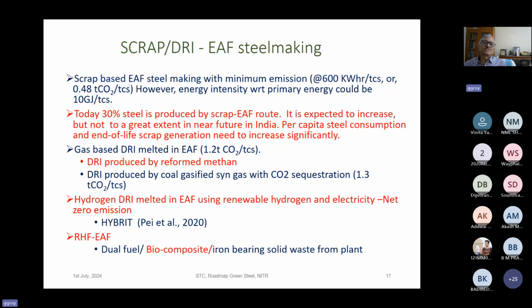Then the scrap EAF steel making. The scrap-based EAF steel making with minimum emission is around 600 kilowatt hour per ton of crude steel, which corresponds to around 0.48 ton of CO2 per ton of crude steel, considering that 1 kilowatt hour is equal to 0.8 kg of carbon dioxide. That is the Indian grid. However, the energy intensity with respect to the primary energy could be 10 gigajoule per ton of crude steel, as I said. Today, 30% of the steel is produced by the scrap EAF route.